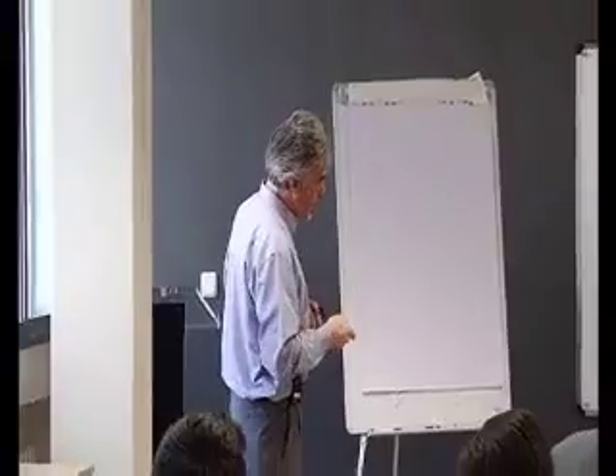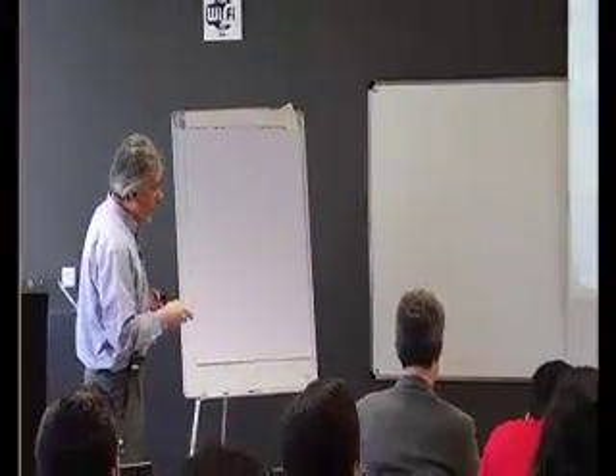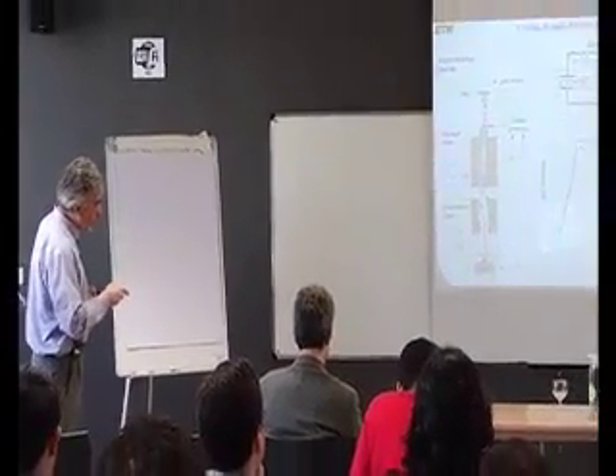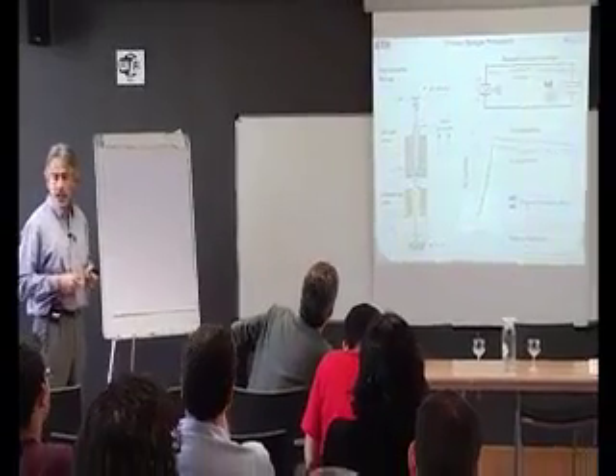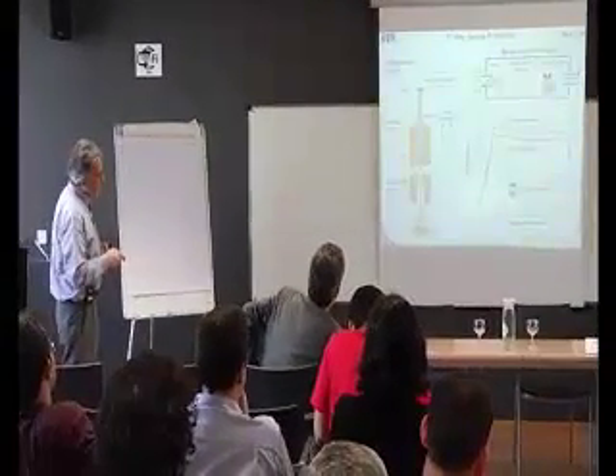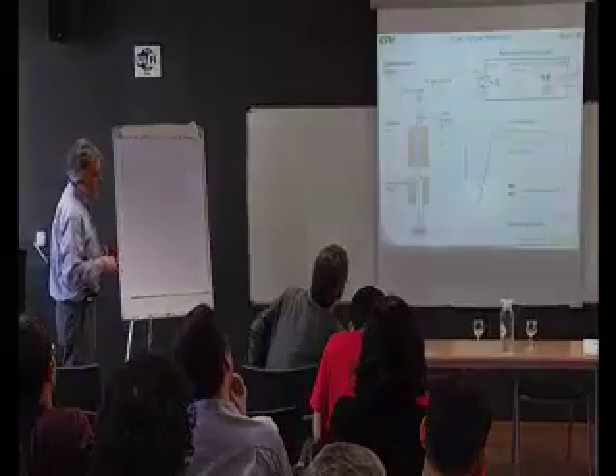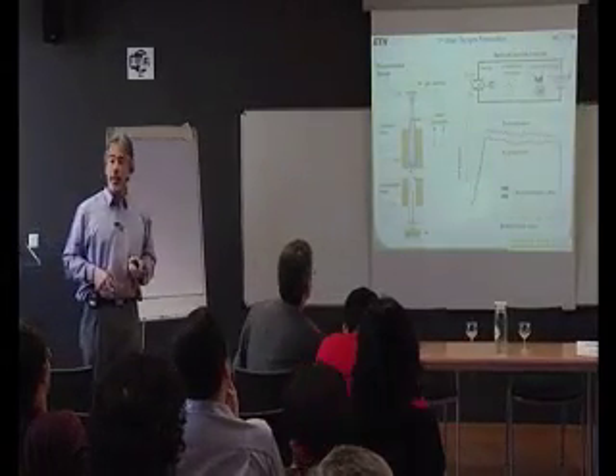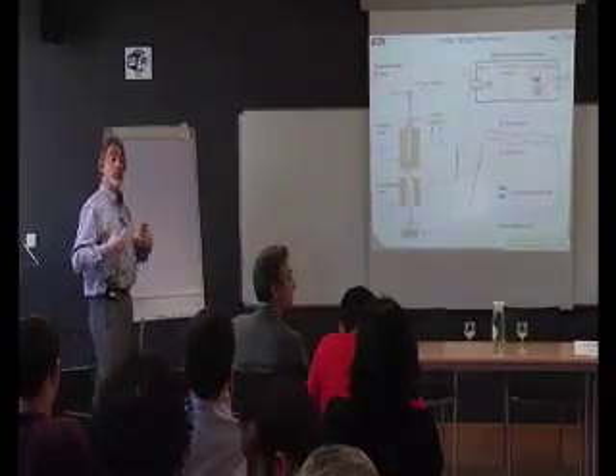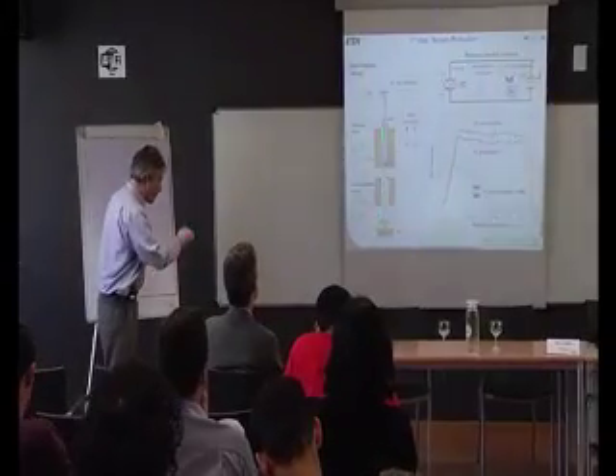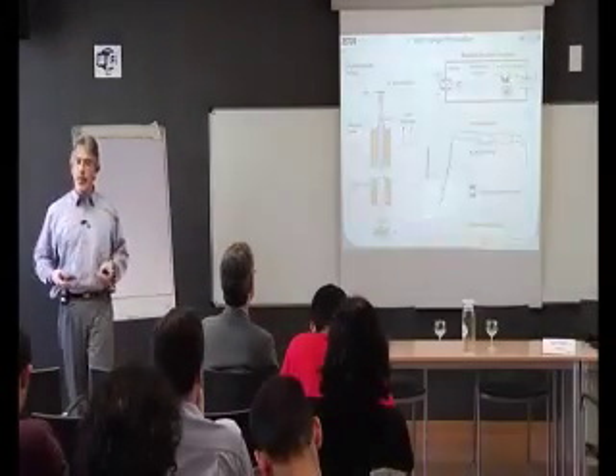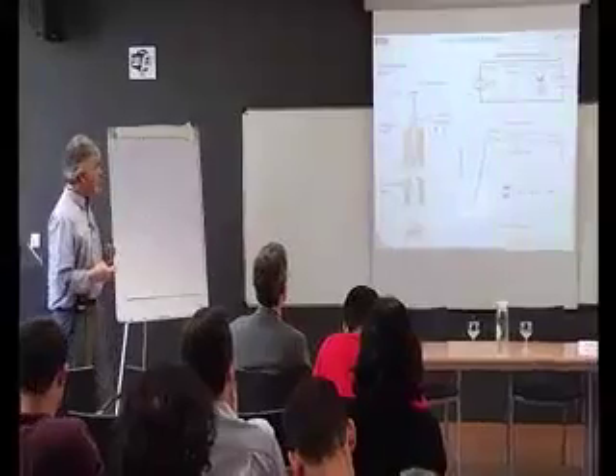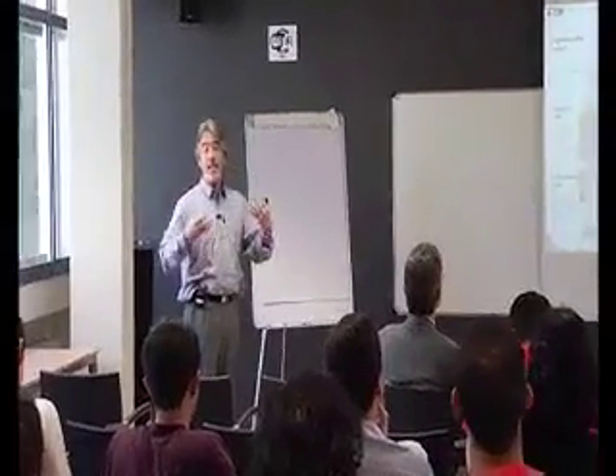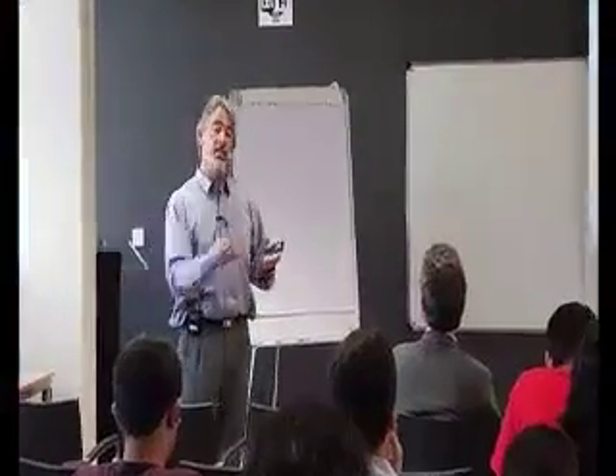This is one of our best experimental results, where you see the zinc evaporation rate, which we measure here, and the hydrogen production rate, which we measure with the gas chromatograph. And if you take the ratio of the two, you get the conversion, 90%. This is a continuous mode reactor. We are flowing zinc continuously and reacting with steam. And the residence time is less than 0.1 second, a very fast reaction.